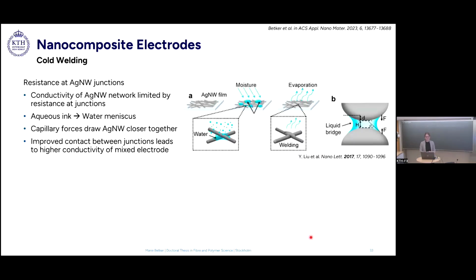And then finally, once this percolated network is formed, the resistance in the electrode depends on the contact resistance between the two nanowires. And you can enhance this by different techniques. You can use mechanical pressing to increase the contact. You can also use high temperatures to melt the metal together. But there's actually a quite smart other approach, which is shown here in this image from this publication.